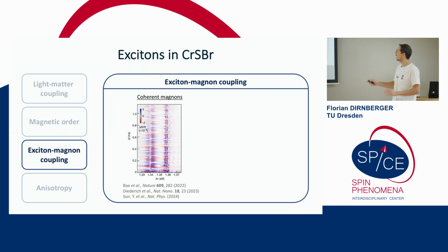There's a couple of other interesting properties of the excitons, but one that is important for this study, I'd like to highlight, goes back to work from Eunice Bae in Xiaoyang Zhu's group at Columbia in 2022, where they showed with this very important and impressive experiment that the excitons and the magnons in this material are coupled. Here you can see how this coherent oscillation of the magnetic order, the spin wave that precesses coherently, modulates the energy of the excitons in time. That's a very important phenomenon. It's also important for the physics that I'm going to show in the rest of the study.